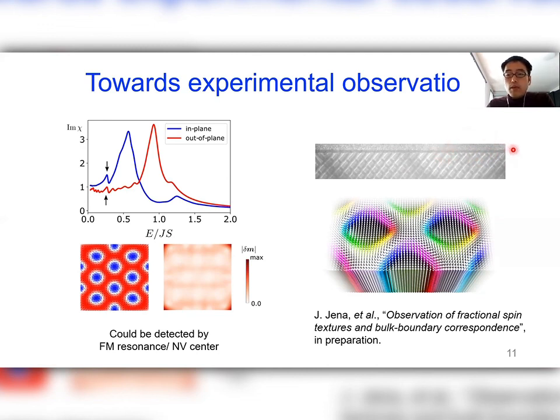Indeed, they correspond to fractional antiskyrmions, which were stabilized at low magnetic field in the Heusler compound. So this experiment suggests that the Heusler material is an ideal platform to search for magnonic corner states, but we should also note that magnonic corner states can be realized in conventional skyrmion crystals, as long as we can stabilize fractional skyrmions. So I'm also looking forward to further studies on these fractional skyrmions in chiral magnetic systems.